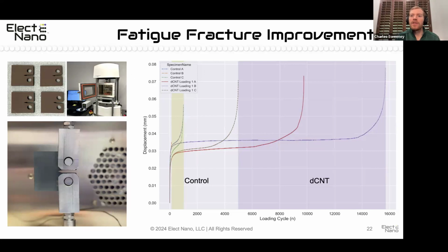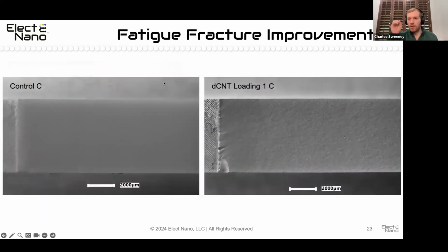And then what this looks like in terms of fracture surfaces, it just jumps out at you. The control samples have a smooth, glassy surface. The surface roughness matches the diameter of the silica filler that's used. It's kind of hard to see, but right here is your controlled crack area for the plastic deformation zone. And on the right-hand side, this line right here represents about a 2x increase in the stable crack growth region before it propagates catastrophically.